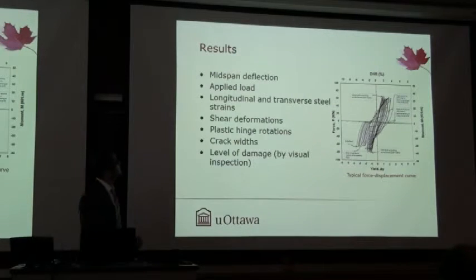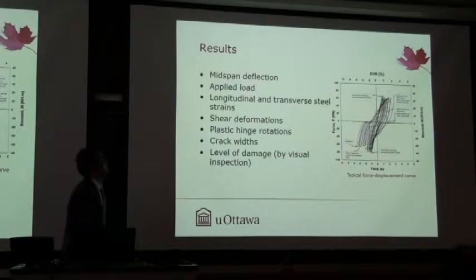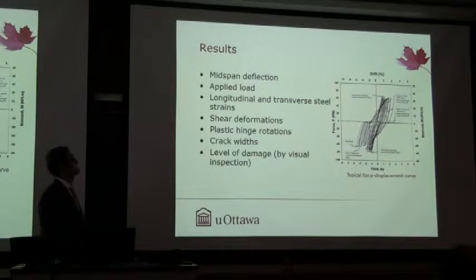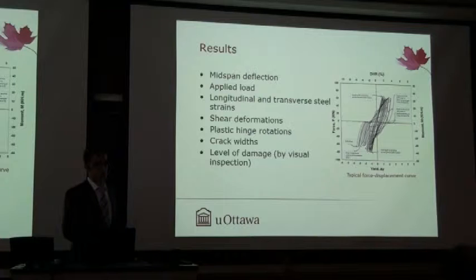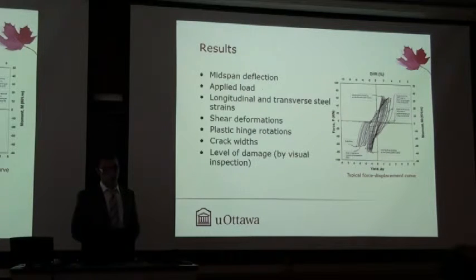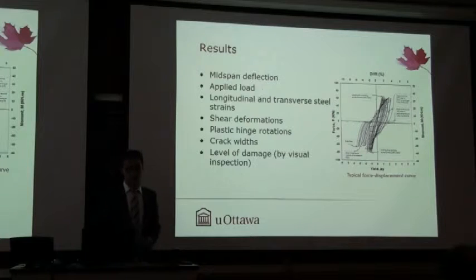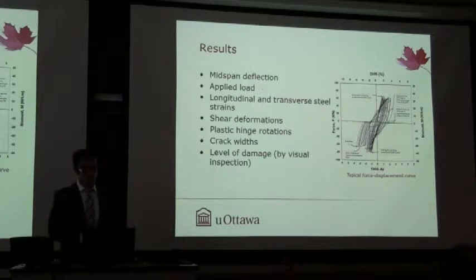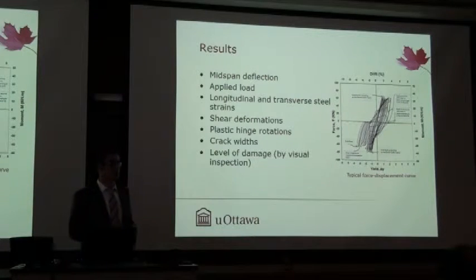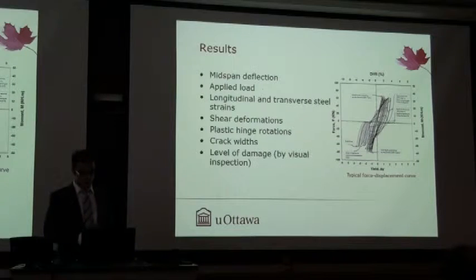As far as the results, we obtained a lot of data from the tests, including midspan deflections, the applied load, which was measured by means of a load cell, longitudinal and transverse steel strains. We measured shear deformations, plastic rotations, crack width, and we also assessed the level of damage to our specimens by visual inspection.